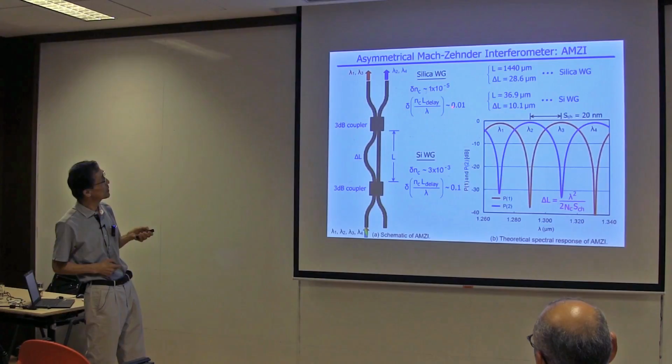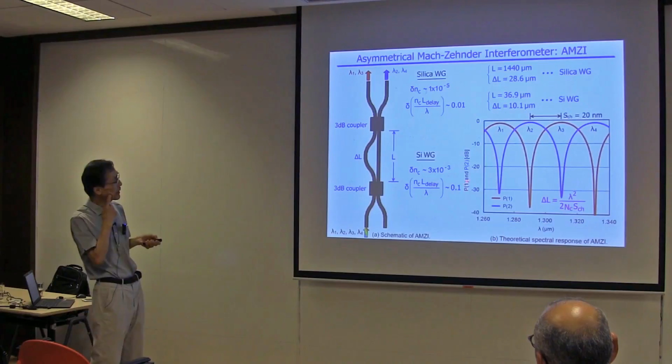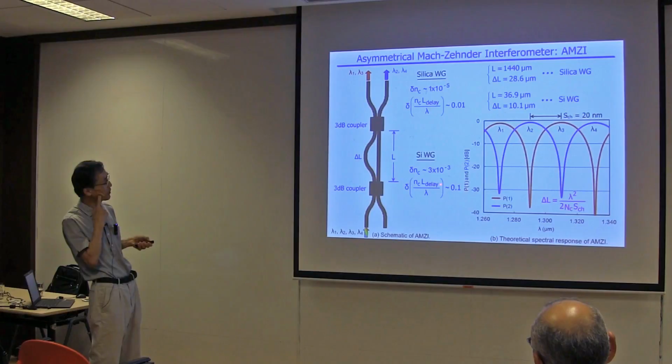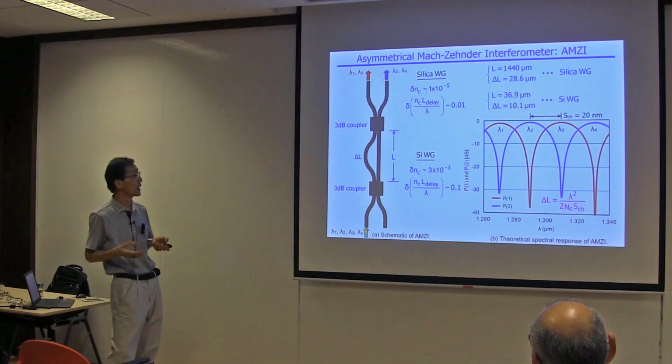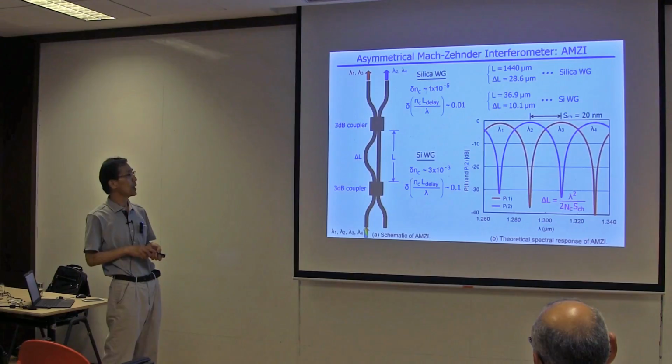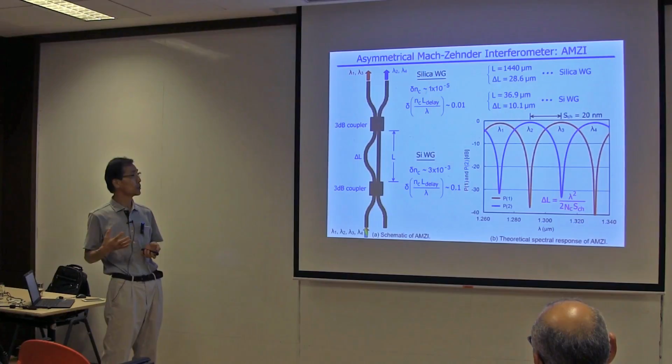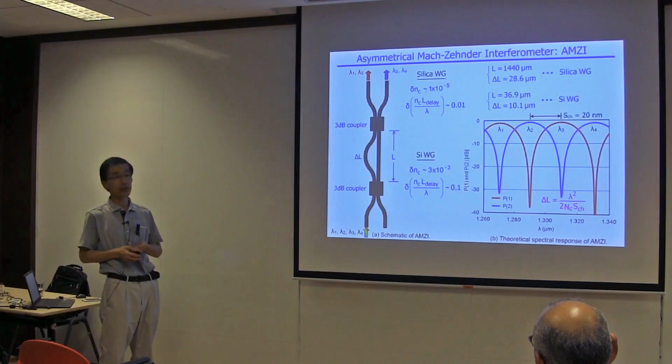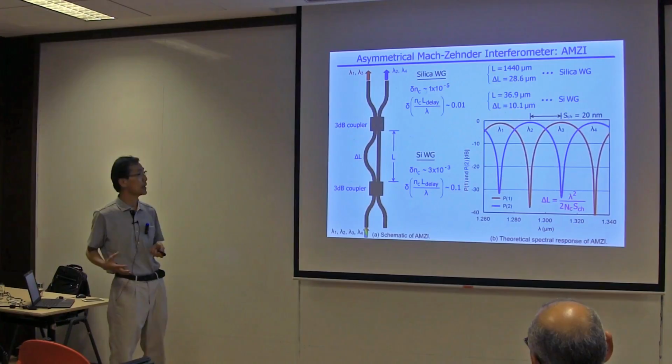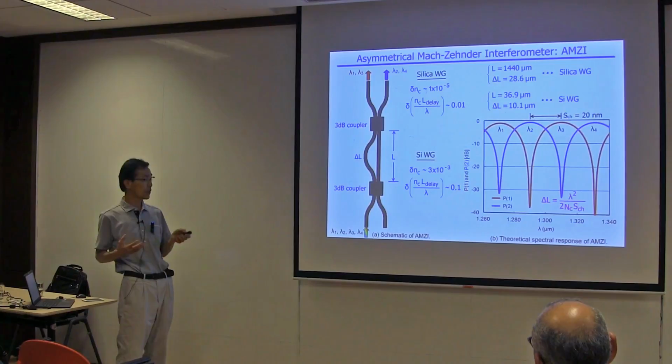If we implement this circuit in silica, the phase delay error is typically 0.01 because of local effective index fluctuations. In silicon, of course, the size becomes very small, but not 100 times smaller, so you should have a 10 times larger phase error in the current CMOS technology. Of course, people have not utilized the most advanced CMOS technique because CMOS people do not allow photonics people to utilize the best advanced CMOS process. It would be very expensive. So what we can utilize even at IMEC, I think, is the one or two generation older process, I suppose.